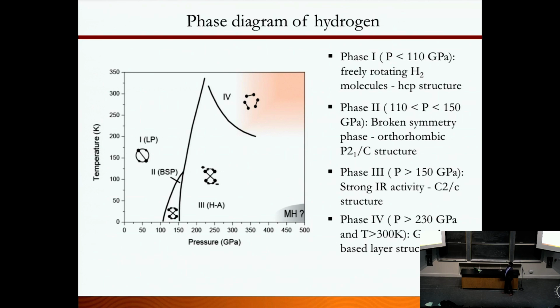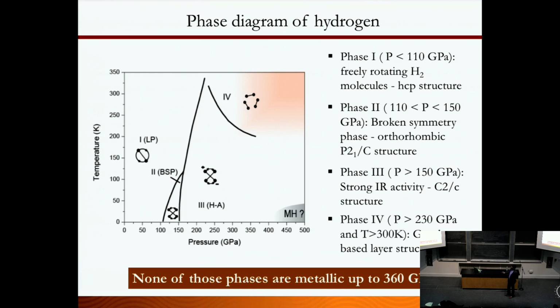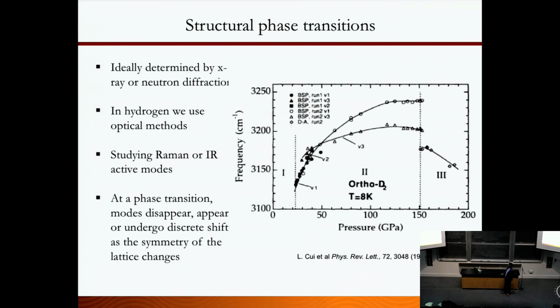And phase IV is another interesting phase. It was recently found at room temperature compression. It has a graphene-like structure, with graphene-like layers. The hydrogen has ring molecules, like graphene layers. So these are interesting structures to study. All of these are studied by spectroscopic techniques, since it's difficult to do X-ray on hydrogen. None of these phases are metallic up to 360 GPa. This is where people have been stuck over the years.